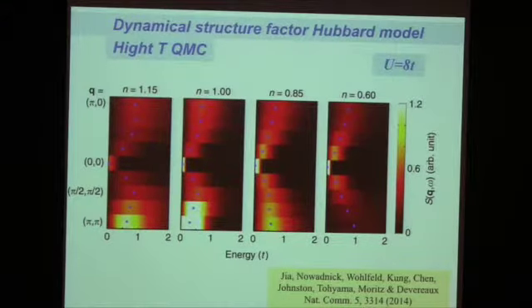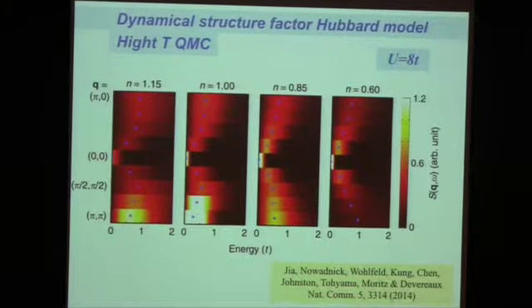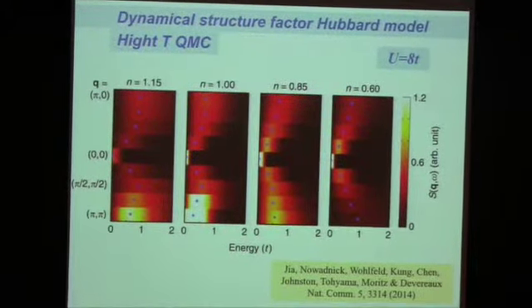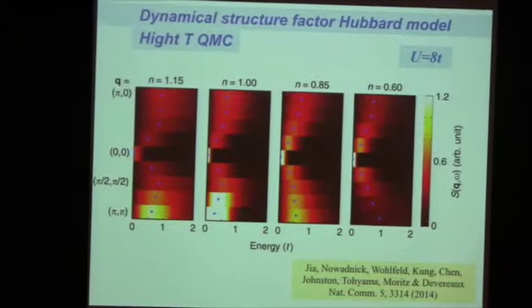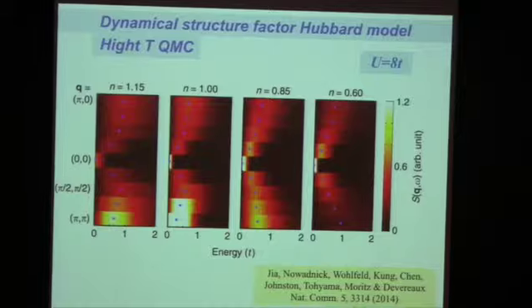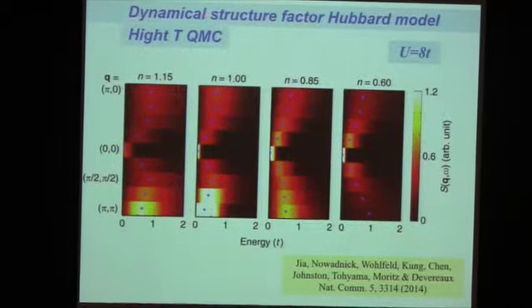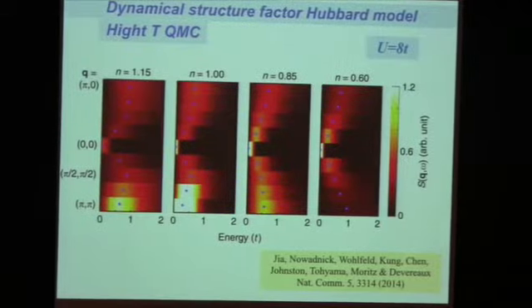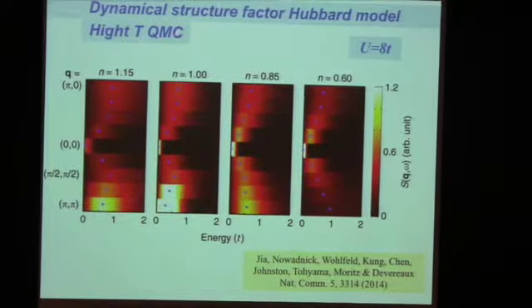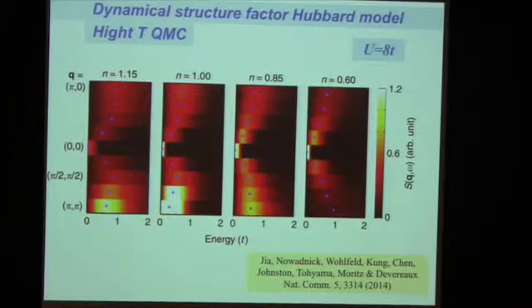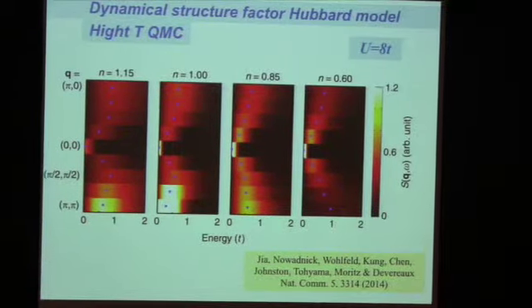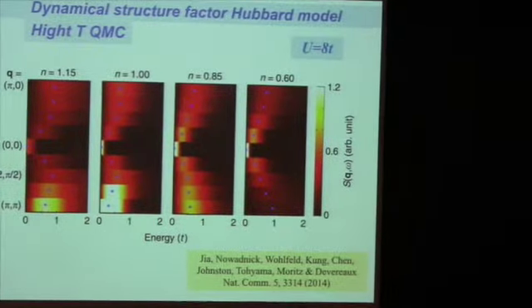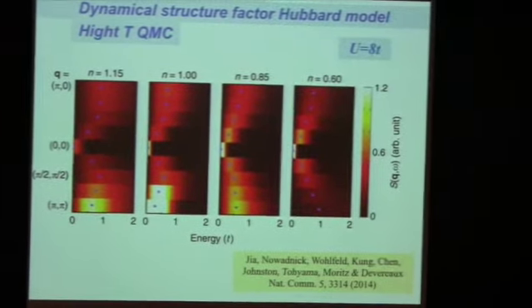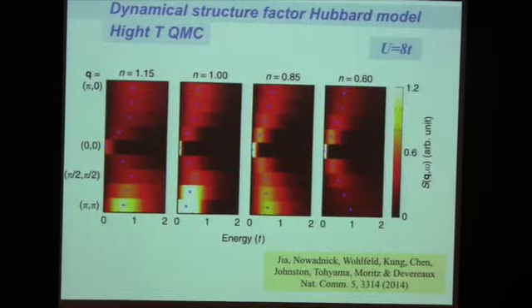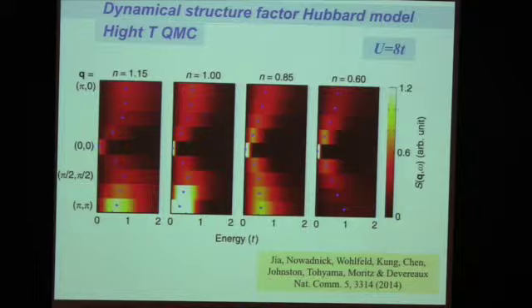Okay, so then you can say, well, let's see what was the first theory done to explain this. At least numerics was done that found a similar effect by the Stanford group. What they did is calculate the dynamical structure factor for the Hubbard model, just S of Q and omega, with quantum Monte Carlo at high temperatures. So the idea is, this is a disordered spin liquid system. If you go to high temperatures, the peaks are broad anyway. Maybe it's not that important that we do a simulation at high temperature. Let's just go with that for the moment.